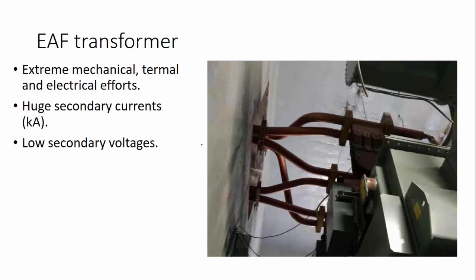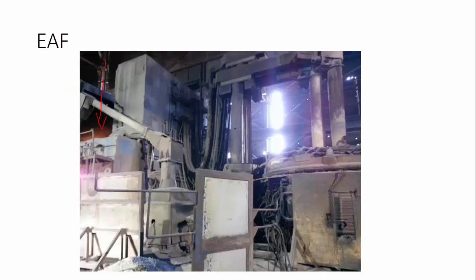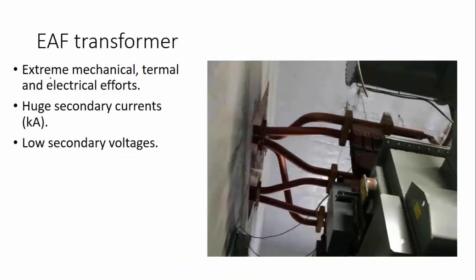Now, when you get closer to the oven, I'm going to go to my first picture. When you get to the transformer that is exactly right behind the furnace, you will find a very specially designed transformer, an electric arc furnace transformer that can handle huge secondary currents, 10, 20 kiloamps, because it's a lot of power at a very low voltage. So these transformers are specially designed because they are subjected to extreme mechanical, thermal, and electrical efforts. The voltage on the secondary of this transformer goes around 660 up to 1000 volts. This is a typical secondary. So you may find this very, very low in comparison to the main voltage for this transformer, which is 34.5 kV. So it's quite a difference in voltage, quite a difference in current.